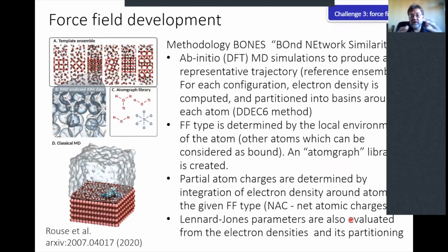Good, so I start now with the detail, how it's implemented. We first discuss how we model surface interactions. And for that, we need a lot of detail, because we want to take into account the exact structure of the surface, how atoms and partial charges are located, how it is hydrated. So hydration effects must be there. How charges interact with each other, how the bulky parts interact with each other, how the surface roughness even at the angstrom scale affects that.